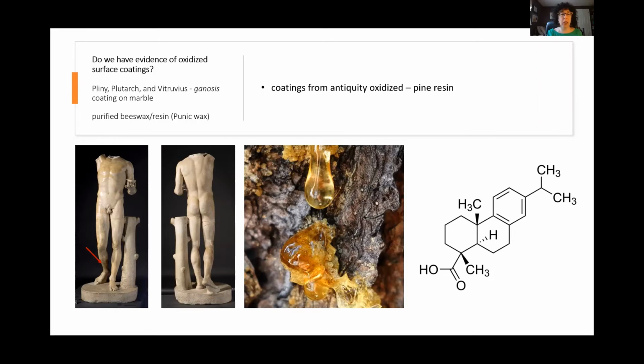And in fact, what we find on the surface of Bacchus is remnants of dehydroabietic acid, and this is the main component of oxidized pine resin. And this oxidized pine resin is a residue not only from antiquity, but of subsequent plant resin coatings that were put on Bacchus as well. And from our microscopy work, we could find at least evidence of 3 campaigns of coatings that had been applied to Bacchus over the centuries.